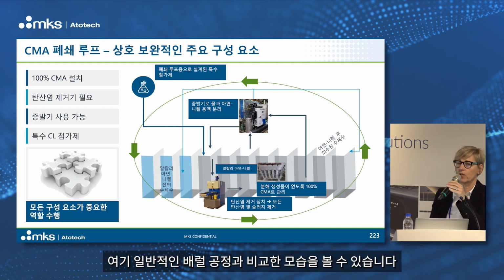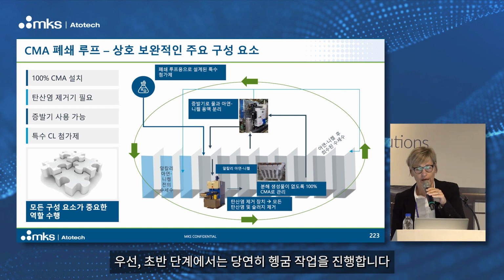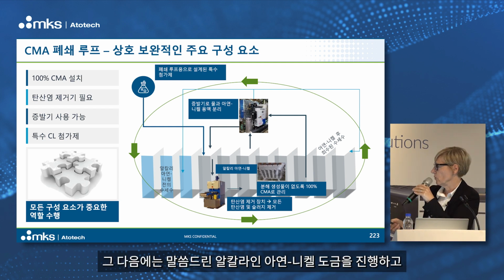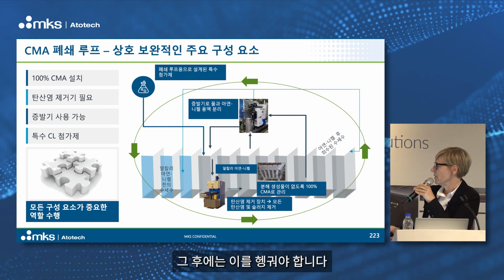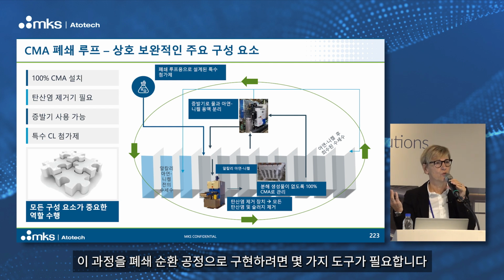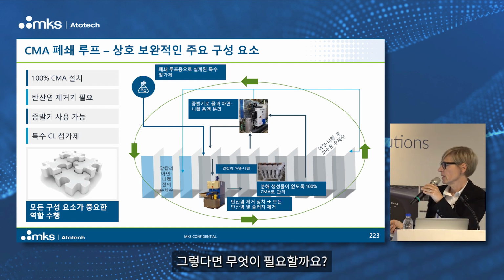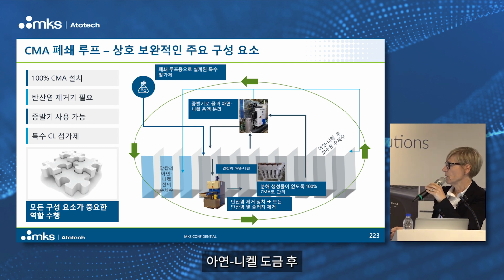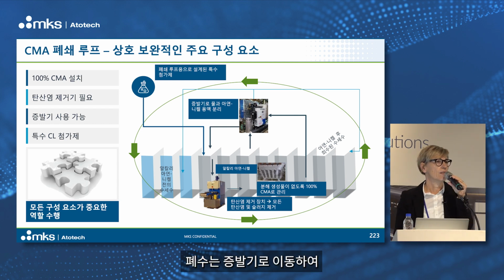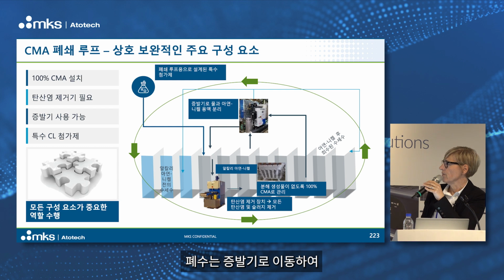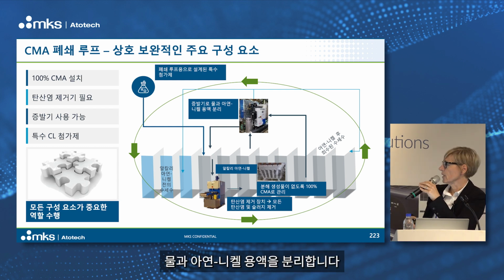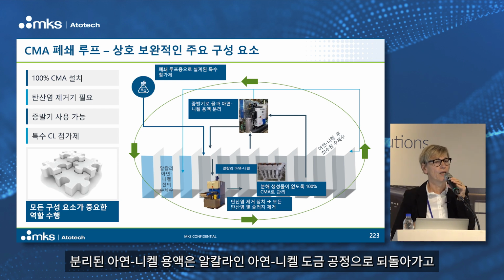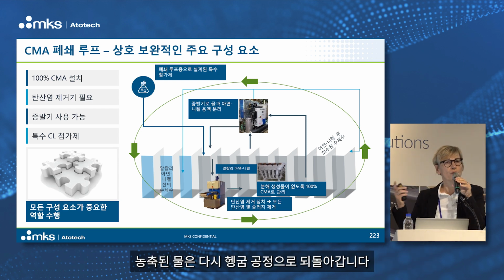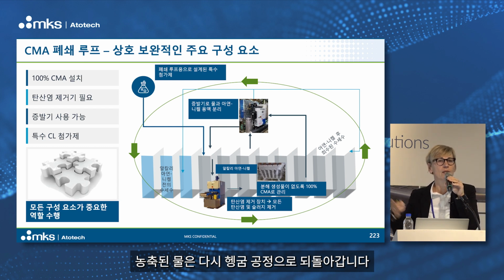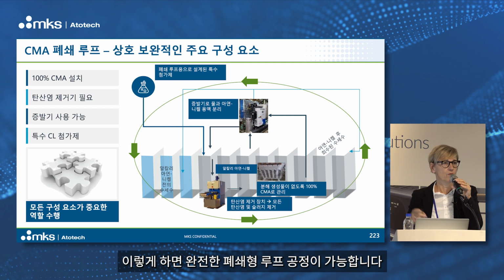You see here the normal barrel process, and in the beginning, of course, the rinsing. Then we have the alkaline zinc nickel, and then we have the rinses afterwards. We need some tools to work in a closed loop, really in a cycle. So what are we using? We need to have an evaporator. After the zinc nickel plating, the wastewater is going into an evaporator, separating the water and the zinc nickel solution, bringing the zinc nickel solution back into the alkaline zinc nickel, and bringing the water, what is condensed, back into the rinse. So this can be done in a closed loop.